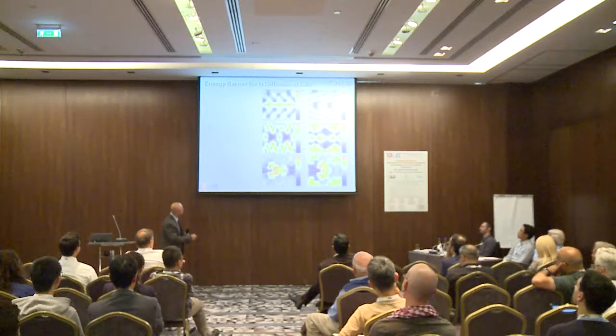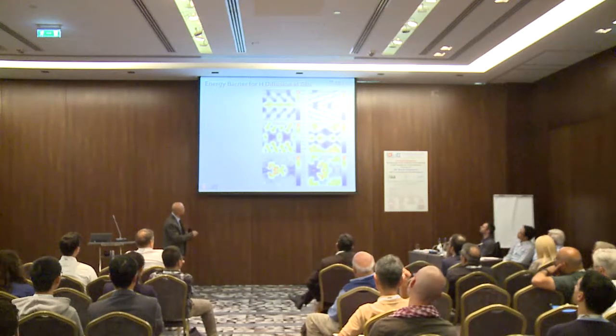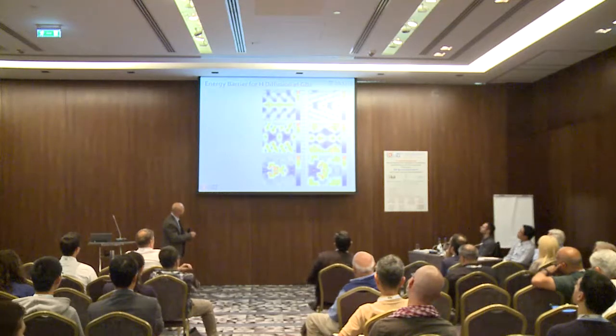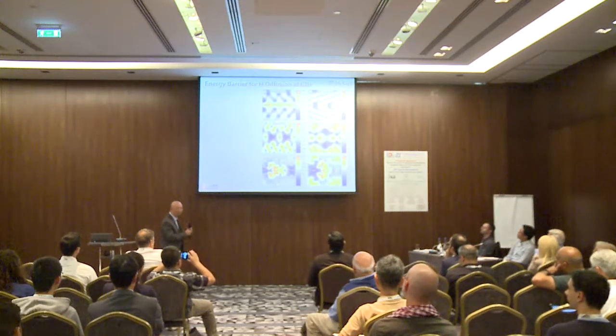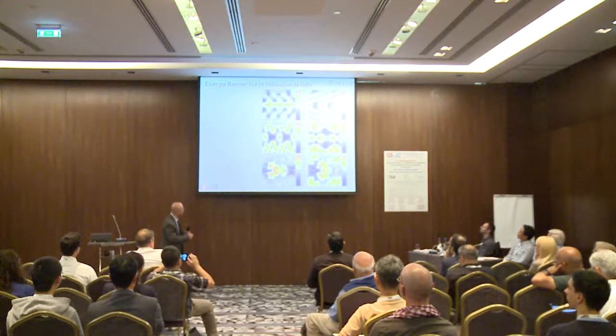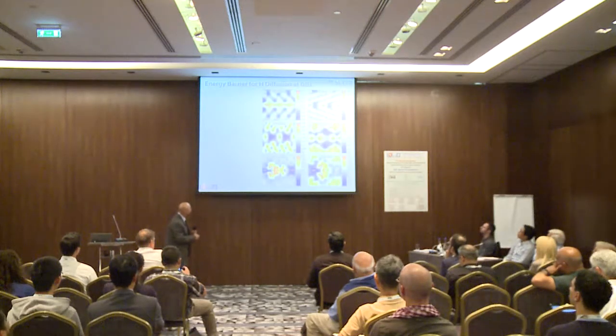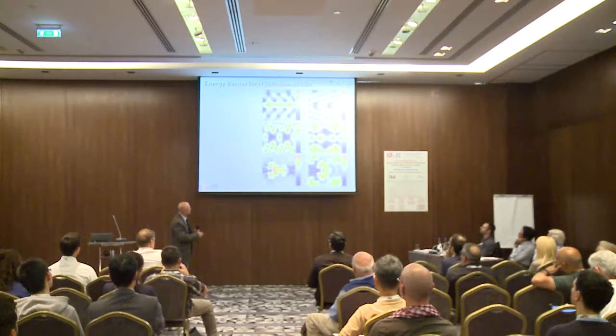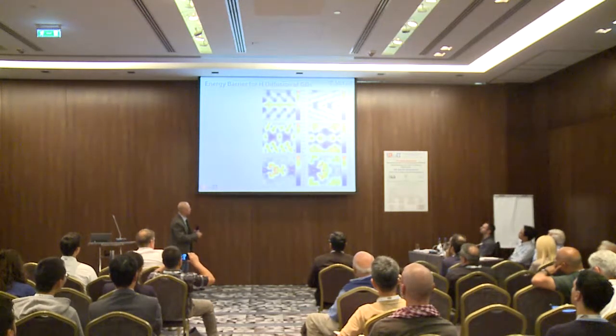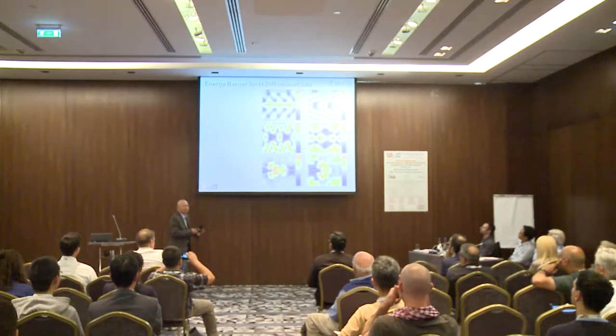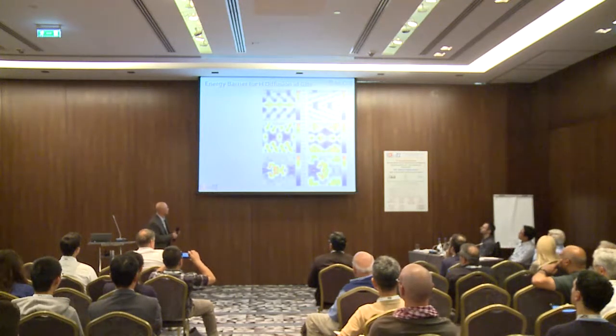For the third row, this is a different scenario again. If you look at localized barriers, you can have low barrier regions and high barrier regions, but the problem is that there's no connectivity. If you look at hydrogen moving around here, it would be very fast. But the problem is that hydrogen cannot travel through the grain boundaries.